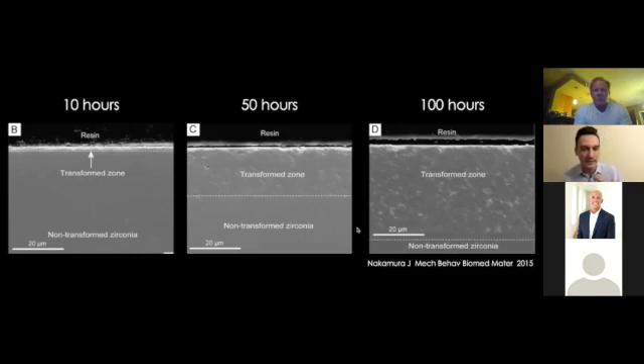The thing that I'm most interested in, and we tried to figure this out, is the depth into the crown. So if you're looking at the crown from the occlusal surface, where is this cracking occurring? Is it cracking a millimeter into the crown, or is it cracking on the outer half of a micron of the crown? And it's really the outer half of a micron. Somebody did this study that found that in a year's time, at regular body temperature, the amount of cracking that occurs is half a micron per year. So that means in like 10 years, you get 5 microns of cracking through the surface of the zirconia.